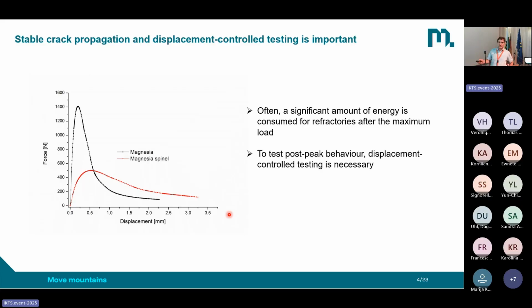What does it mean now for us? If we would do a force-controlled loading, then the test would end here at the maximum force. Why? Because the machine is further increasing the force with a defined rate, for example, in newtons per second. And then we reach a state where the sample is not stable anymore because we further increase the force. Fracture would happen. In this case, then a diagram would look like this, that we reach this point and then we have an immediate fracture. No further displacement can be applied.